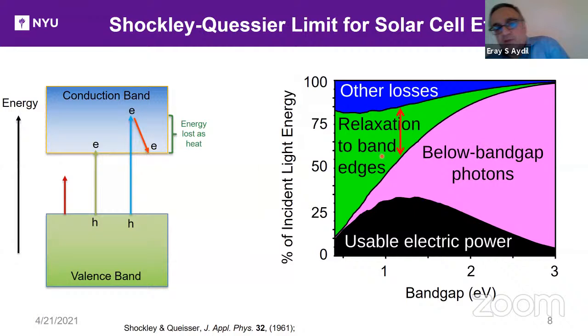So that energy that goes to heat, that energy lost as heat as the electrons relax to the band edges, is actually quite a lot. Here is that maximum, the usable electric power is underneath that. The pink here are the band gap photons, that are photons with energies below the band gap. And this green here is the amount lost as heat, relaxation to the band edges. And that's quite a bit. How to recover that is a worthwhile thing to think about.